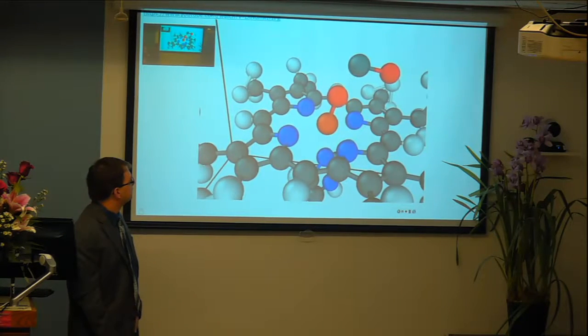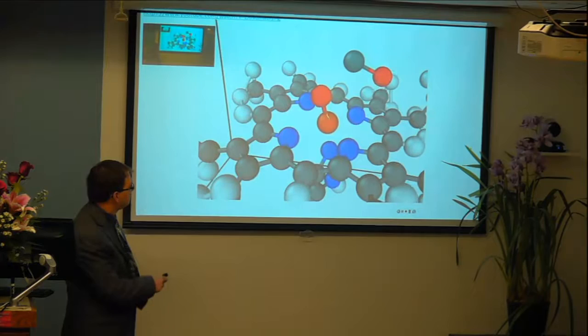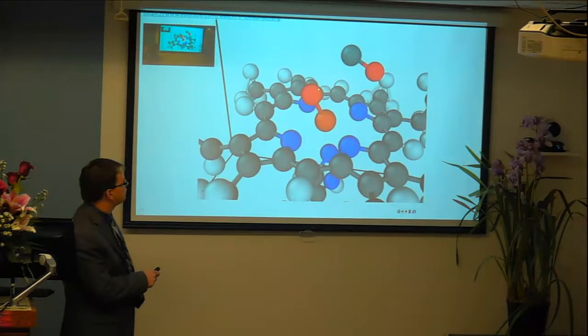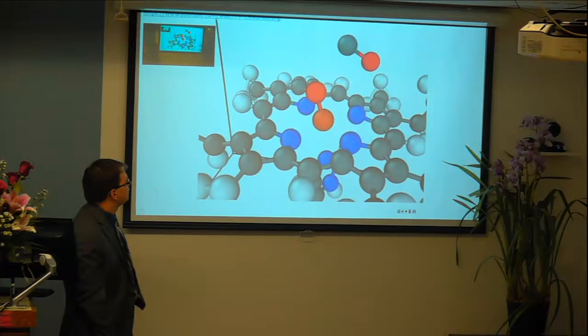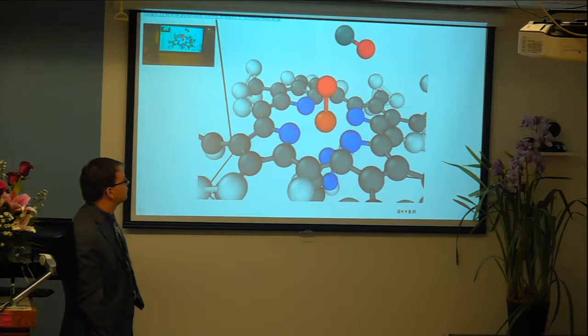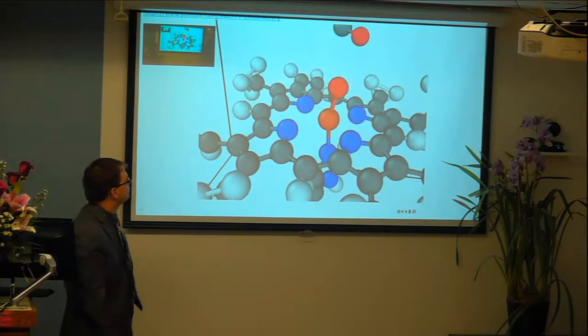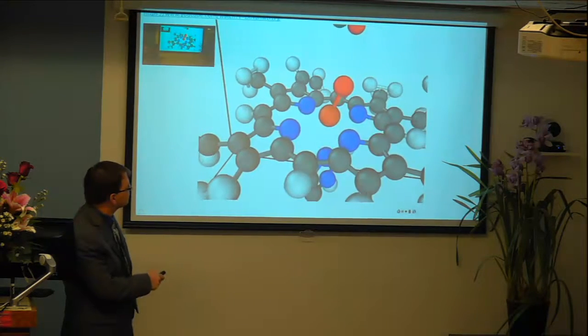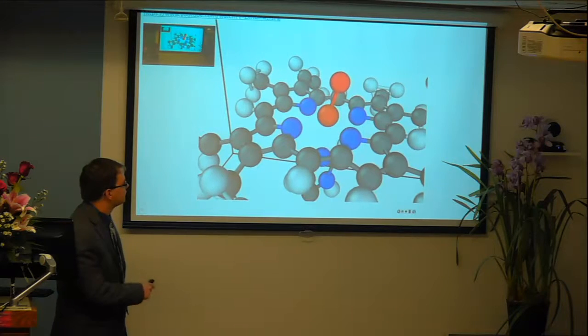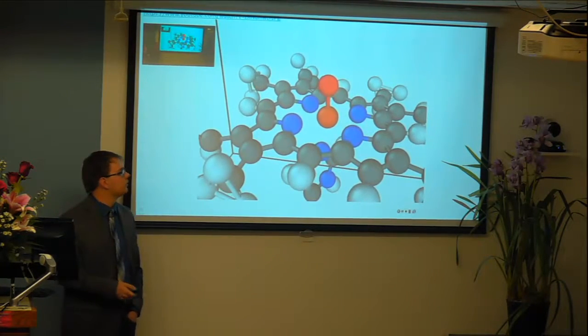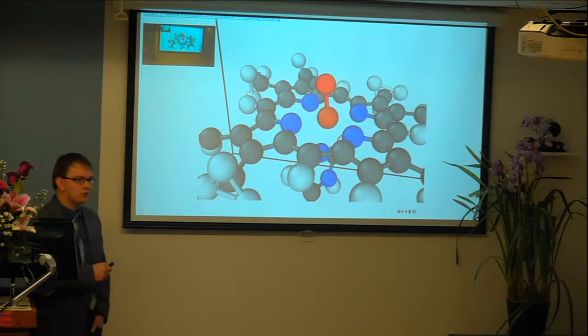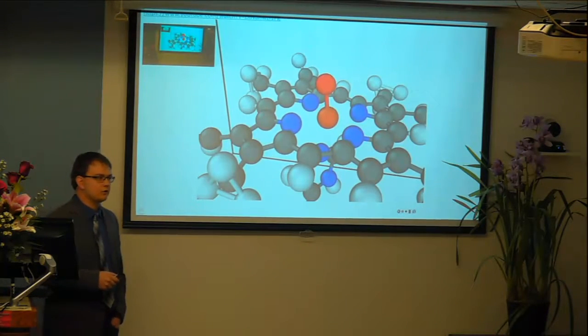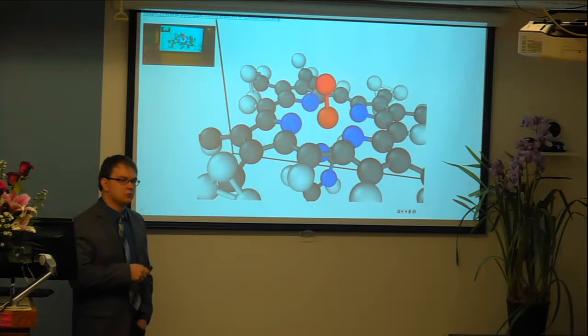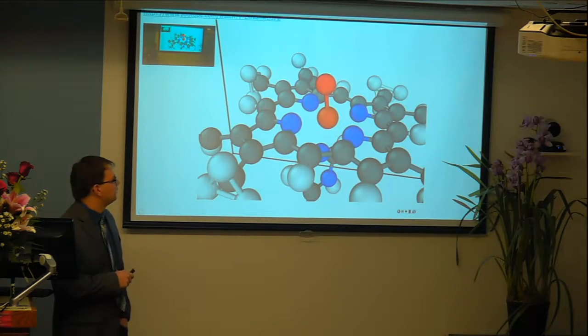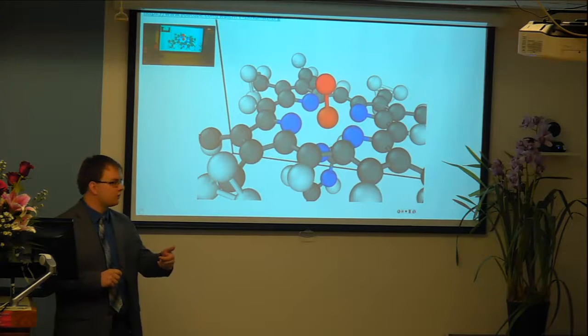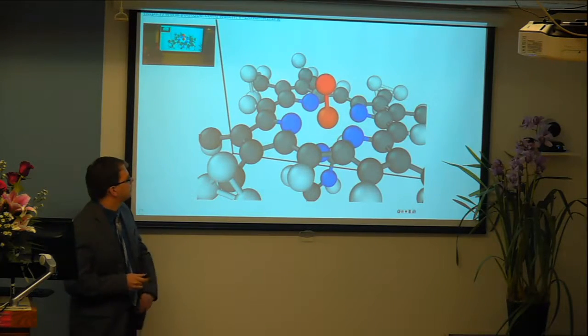So you see kind of the artificial bond, of course, but the iron has kind of snatched that oxygen from the chloride, and the chloride has some residual momentum, of course, so it goes on, but retains this oxygen. So this is the first step in the hypothesized reaction. And so now this is where the hypochlorite might be stabilized sterically or coulombically by a nearby charged species, and then it may flip around to create that peroxide linkage that is also hypothesized.